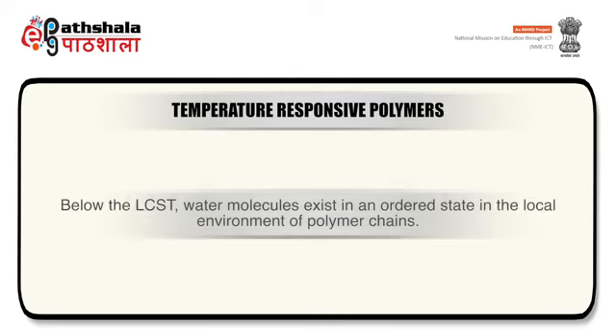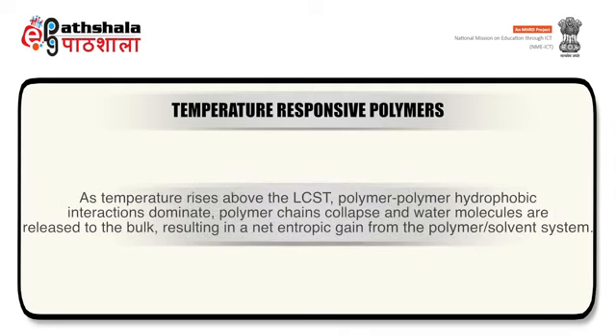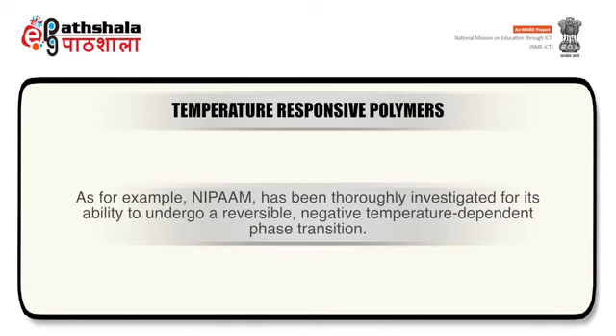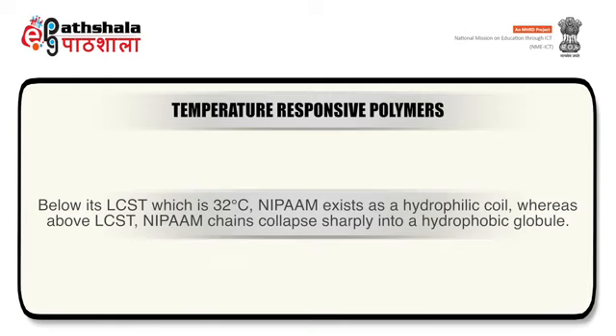Below the LCST, water molecules exist in an ordered state in the local environment of polymer chains. As temperature rises above the LCST, polymer-polymer hydrophobic interactions dominate, polymer chains collapse, and water molecules are released to the bulk, resulting in a net entropic gain from the polymer solvent system. For example, NIPAM has been thoroughly investigated for its ability to undergo a reversible negative temperature dependent phase transition. Below its LCST, which is 32 degrees Celsius, NIPAM exists as a hydrophilic coil, whereas above LCST, NIPAM chains collapse sharply into a hydrophobic globule.